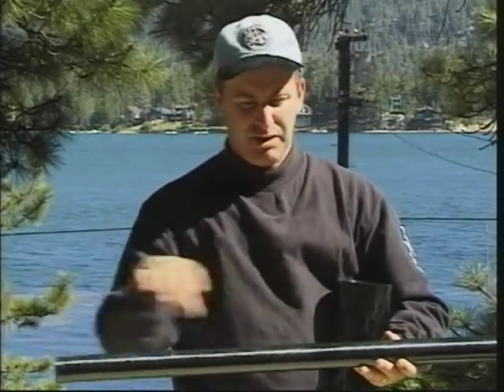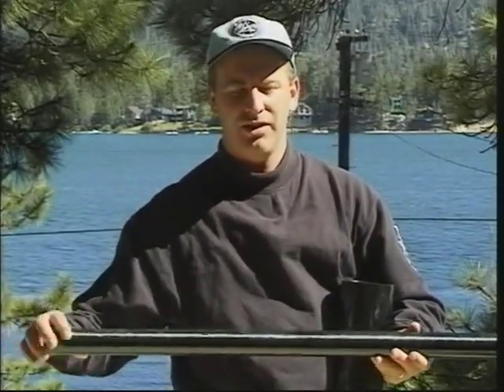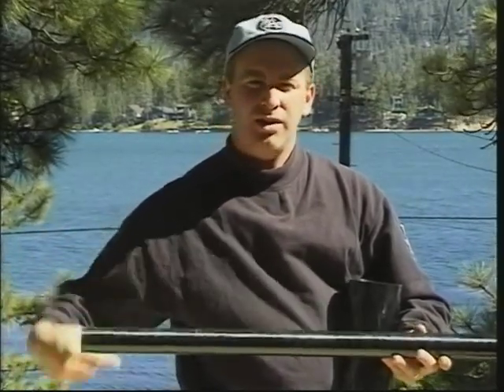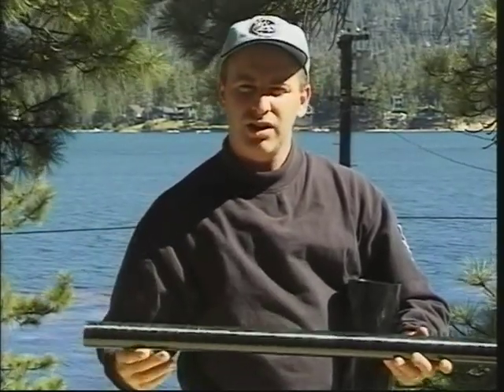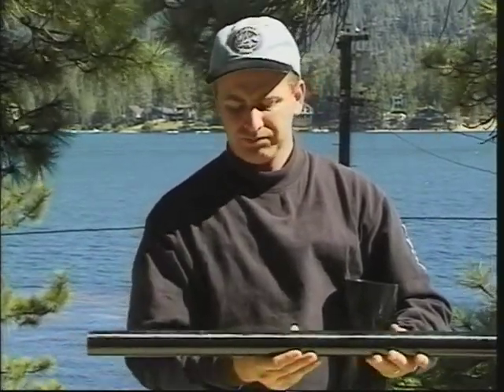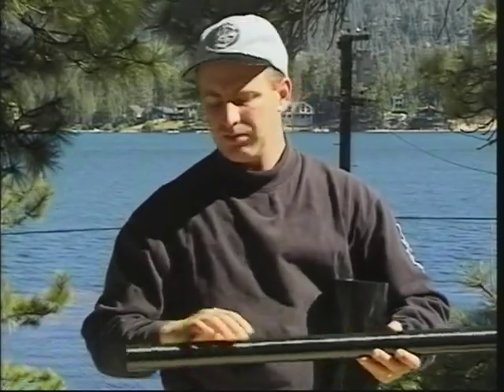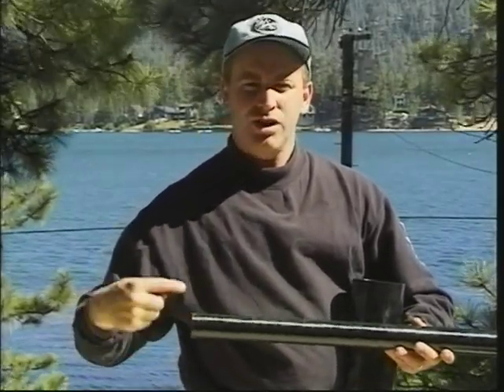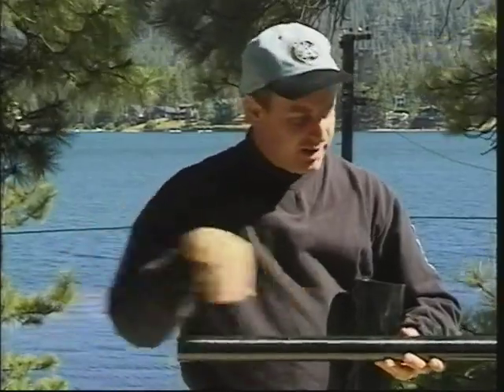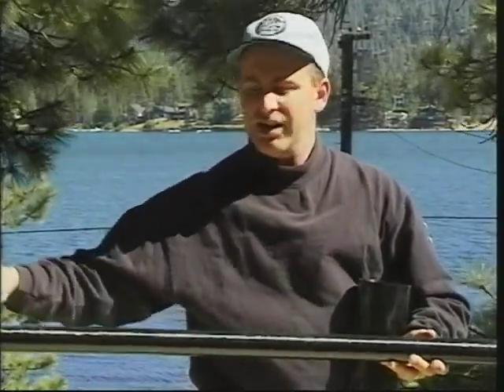This tube is wound around a tool, or a mandrel as it's called, which is polished stainless, just a big long cylinder of polished stainless in the right size. It's wound around that by a filament winding machine, that winds with an individual fiber yarn, essentially, called tow, of carbon fiber around that in specific directions. This one, on the inside of the tube, is wound at -10 degrees relative to its length. The second layer is a longitudinal layer at 0 degrees, and then the third layer is at 10 degrees.